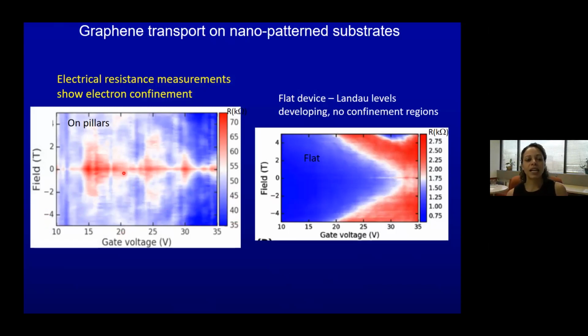And the thing to point out here is first that on the left is graphene that's on the pillars, and the right is flat graphene for around the same range. And you can clearly see a difference. In fact, for the flat graphene, looking at high magnetic fields, we get the beginning of Landau levels, which is field-dependent cyclotron motion. Whereas for the graphene on pillars, there's no features. This whole region in here, there's almost no features, okay?